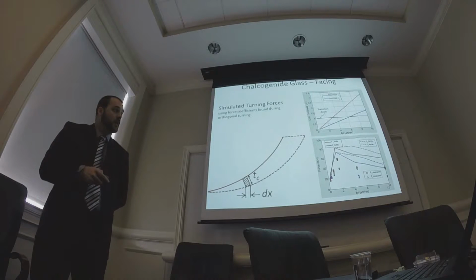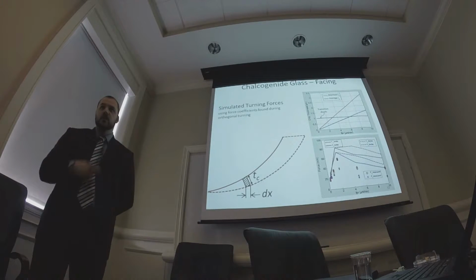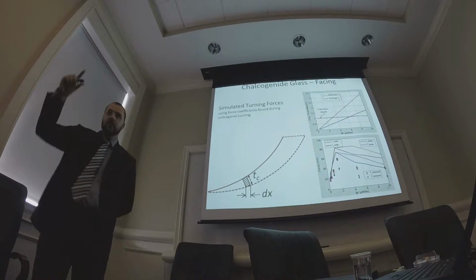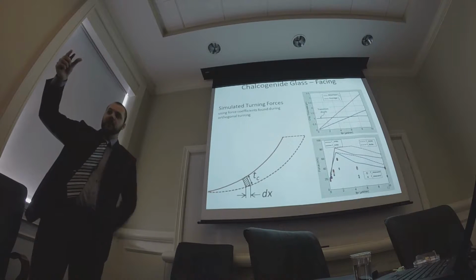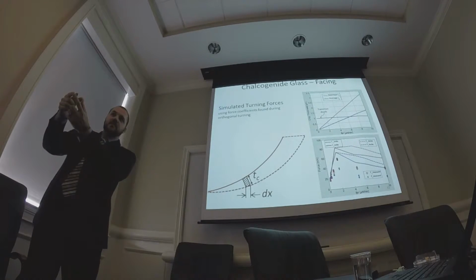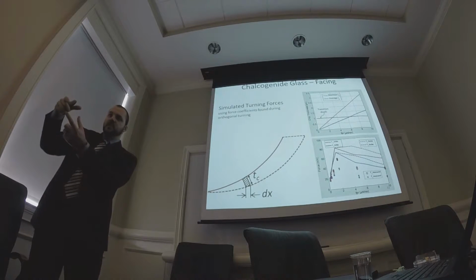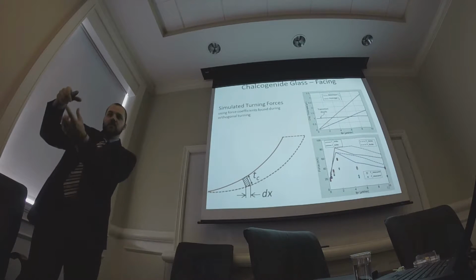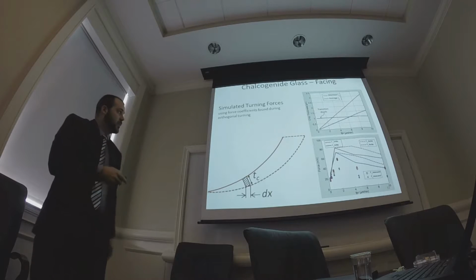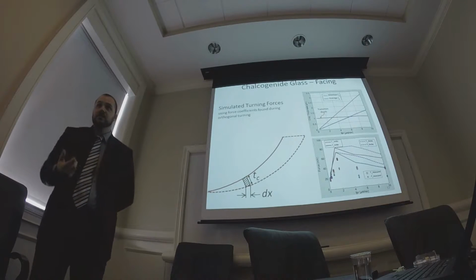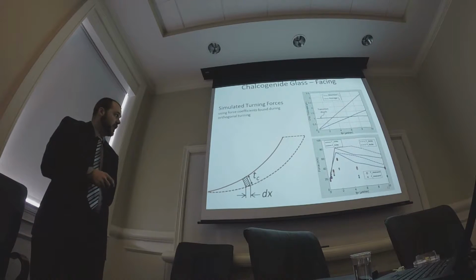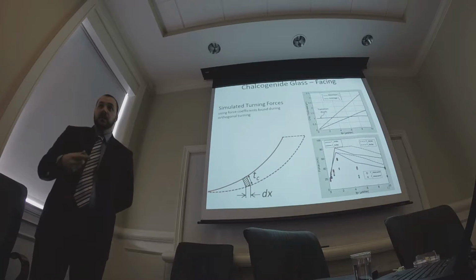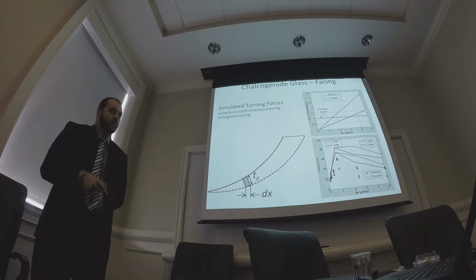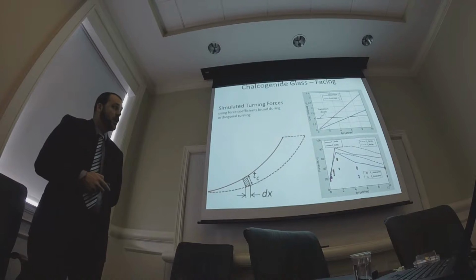So the way that I see these results is when we're turning, fracture's occurring up higher, and that fracture is sitting right next to where there's not fracture. And since we've got this hysteresis, the fracture is going to sort of propagate its way down the tool. Then when we get to a thickness, which I'm assuming is around 700 nanometers, the rest of it will continue to be ductile, but the fracture is going to propagate all the way to that point. So it makes sense to use the bottom side of that hysteresis curve for our force coefficient.